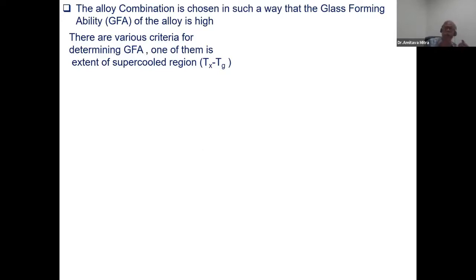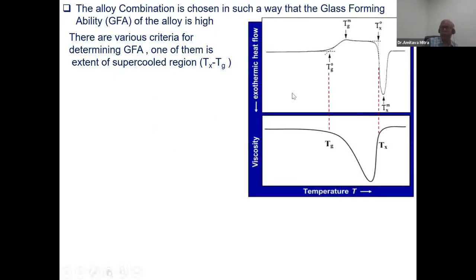When this glass is forming, if we heat it, we get Tg, the glass transition temperature. If we go further heating, we get the crystallization temperature, Tx. The difference between these two, Tx minus Tg, is defined as the glass forming ability of this alloy. Usually this goes to 50 degrees or more for good glass forming ability.